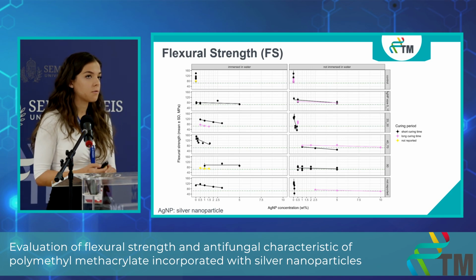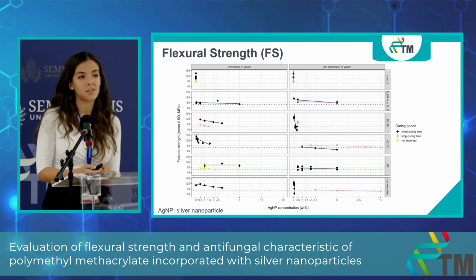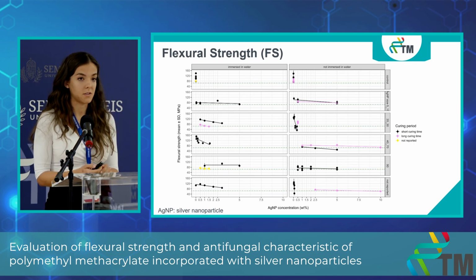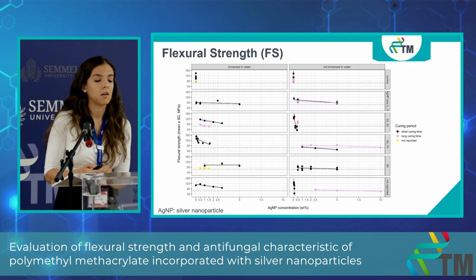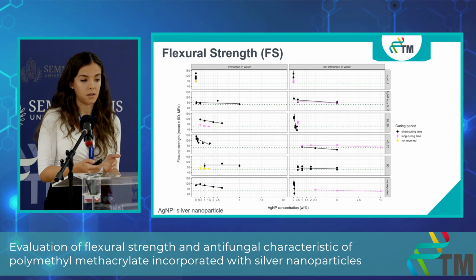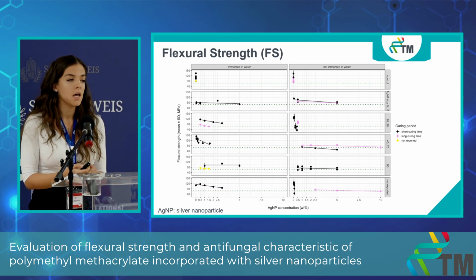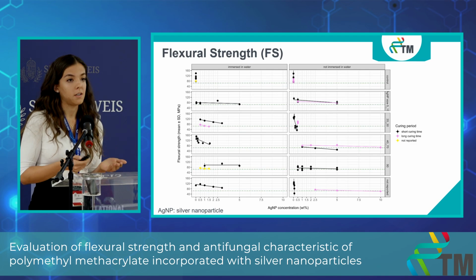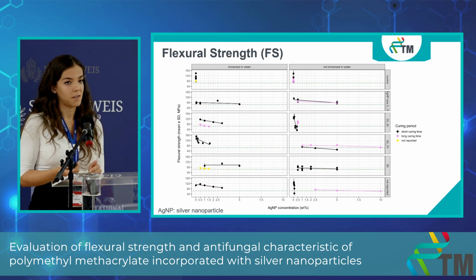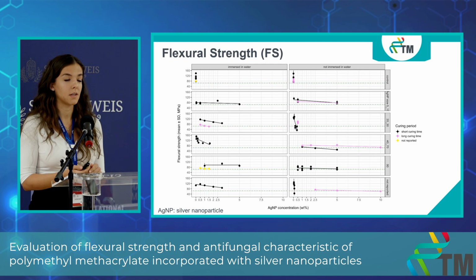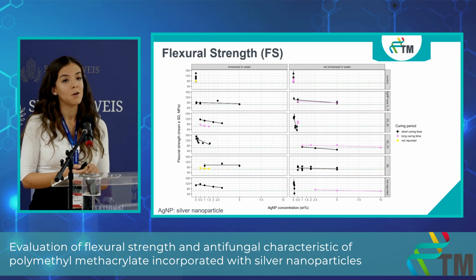And to sum up the results for the flexural strengths: it significantly decreases as the silver nanoparticle concentration increases. And the effect of the other factors like the immersion or non-immersion, polymerization technique, and the size does not show significant differences. But there were numerical differences, so it is worth to further investigate these factors. And in terms of the long polymerization technique, we need more data and studies.